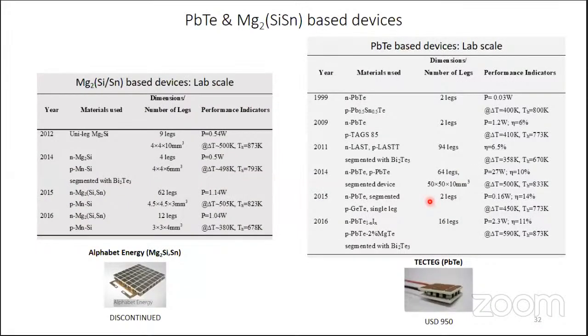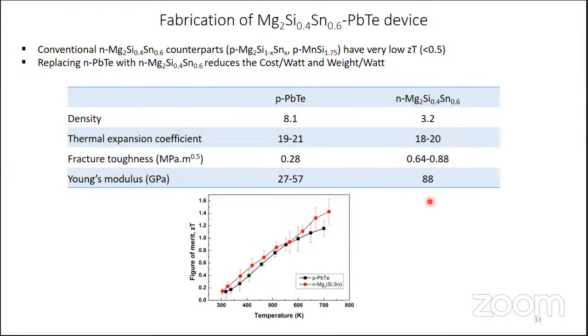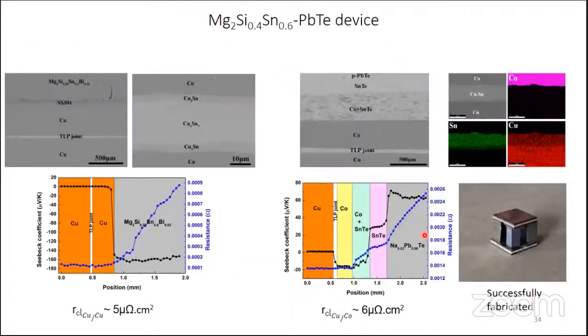And of course, these are the previously reported devices by other labs, and nobody has used this combination of materials like Mg2SiSn and lead telluride. We successfully used it because this combination has comparable thermophysical and thermochemical properties. You can see that the thermal expansion coefficients almost match in these two cases, almost like the same material. This is very important because both legs undergo the same temperature, so they should expand uniformly so that no stress is created and there is no cracking. So these properties are matching. That is why we took the pair, and the figure of merit is also almost comparable up to the proposed hot side working temperature.